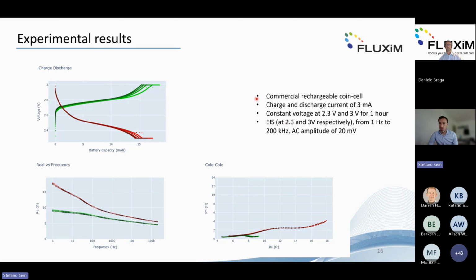commercial rechargeable coin cell with a charge current of 3 milliamps, a voltage range of 2.3 volts down and 3 volts up. And then there was also a constant voltage step of 1 hour at the end of the charging phase. And then impedance, as I said, was done at the end of every charge and discharge cycle, from 1 Hertz up to 200 kilohertz with an AC amplitude of 20 millivolts. Here it's just the impedance enlarged.